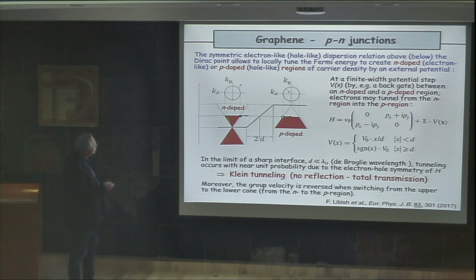However, if you look carefully at the section of the cone, this is the section of the upper cone, and this is the section of the lower cone here, what you see is that for a certain group velocity, the ky component goes to the other side when you go from the upper cone to the lower cone. So you have a reversal of the group velocity of your Dirac fermions.